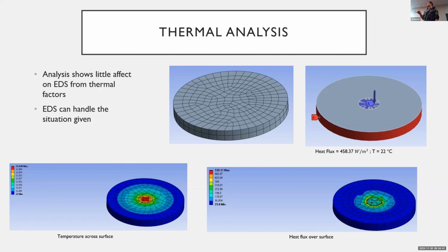So in the middle image at the top, we have our mesh for the electrode. And at the top right, we have the boundary conditions for our electrode. If we assume it's a cylinder, the outside is going to be at a temperature of about 22 degrees Celsius. We assume that because we are placing our EDS on the inside of the landing gear, away from any lunar regolith, so it won't be compromised. The astronauts are also inside the spaceship, so we assume ambient temperatures for the general inside of the HLS.